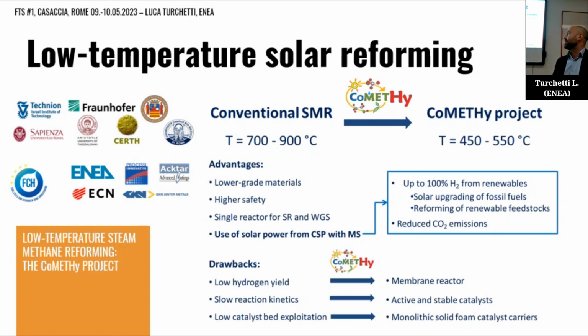Of course, there are several drawbacks. The first one is the low hydrogen yield, which is addressed, as we're going to see right away, with a membrane reactor. You get slower reaction kinetics compared to the conventional process. And then you have to develop active and stable catalysts also in this lower temperature range. You also need a reactor catalyst bed which is very effective in transporting heat, because ensuring a good heat transfer and uniformity of temperature in the bed of the reactor is especially important in the case in which the reactor operates at lower temperature. The reason why you operate this process conventionally at 700 to 1000 Celsius degrees is because otherwise you get a very low hydrogen conversion, which is not industrially feasible.